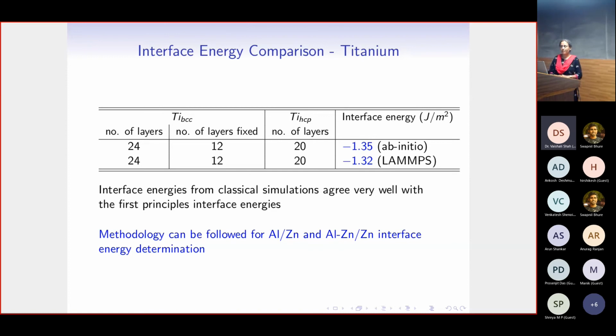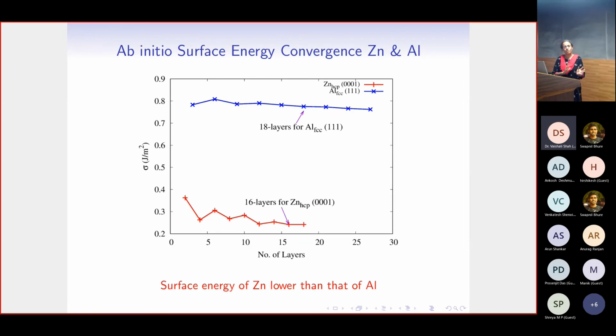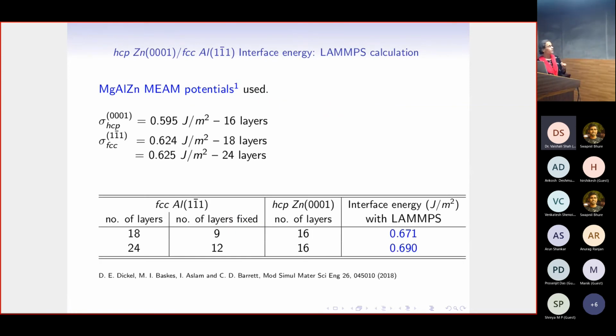So now that we have been able to validate that we can work with classical simulations, we have a methodology that will work for aluminum zinc and any other metal alloy interface that we are interested in. We follow this titanium procedure for the aluminum zinc alloy. We do the surface energy convergence for the aluminum FCC 111 oriented surface, and for the zinc HCP 0001 oriented surface. The first observation is that the surface energy of zinc is much lower than that of aluminum.